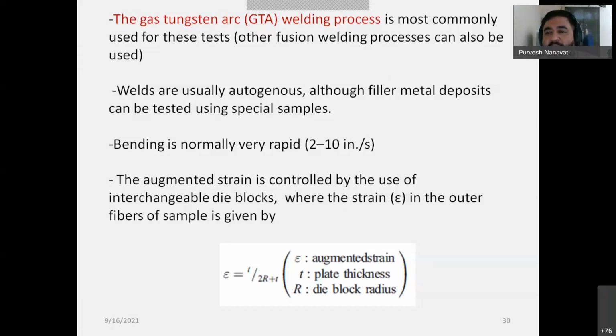It is 2 to 10 inches per second only. So it's a very fast bending. You could see it in a video. And now, the most important quantification part is here. The augmented strain is controlled by the use of interchangeable die blocks. Now, augmented strain means, you know, the varying degree of strain, because we have known this word, varestraint. So variable strain. So augmented means which you can keep on changing by changing the die blocks.